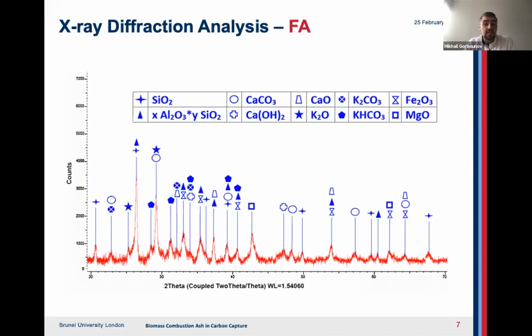Nevertheless, magnesium oxide still can't go unmentioned, and in the conventional calcium looping process, this chemical, which is also seen in our fly ash, is used as an additive to the capturing media in order to improve cyclic stability. Plus, the carbonation reaction occurs at much lower temperatures for magnesium oxide in comparison to calcium oxide. Though calcium species are still valuable for carbon capture and are also present in our material in the forms of calcium oxide and calcium hydroxide.